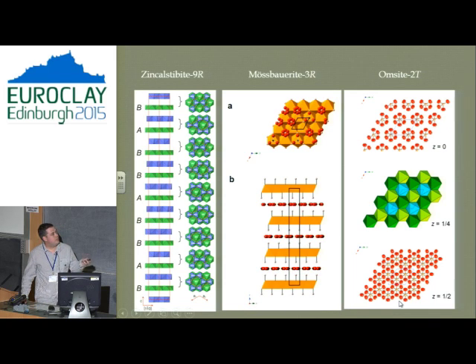The most common polytype is this one here. This is for a Mössbauerite, 3R. So 3R, we have the metal octahedral layers, and in here we have the carbonates and the water. What's common in the antimony ones is T structures. So here is a 2T where we've got nickel and iron at a 2-to-1 ratio, and then we have antimony in the interlayer.